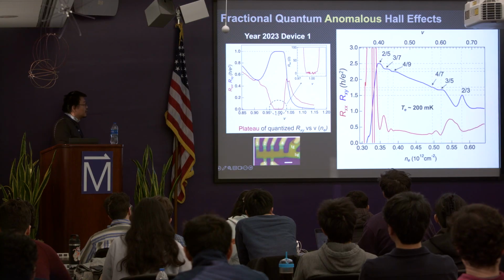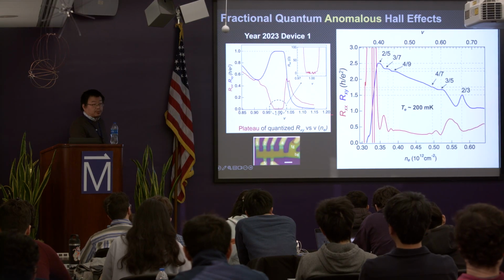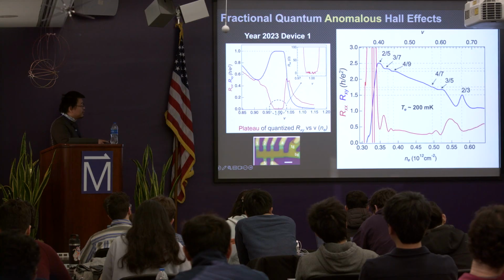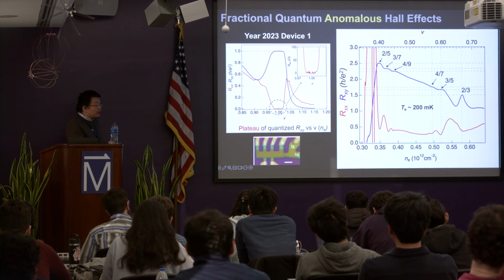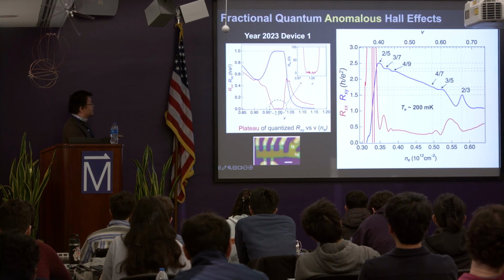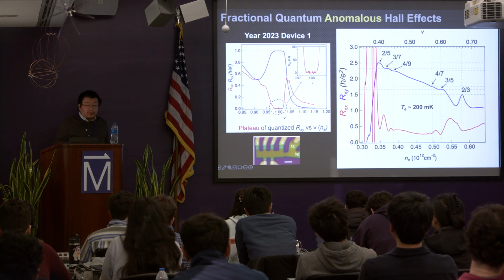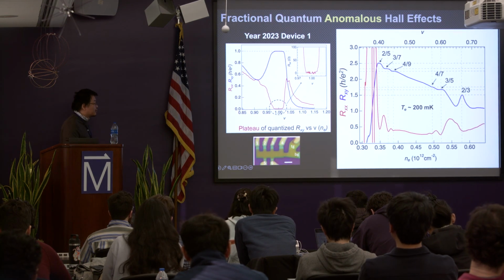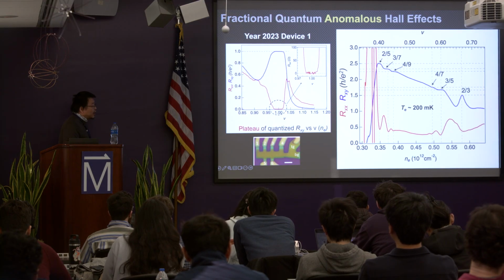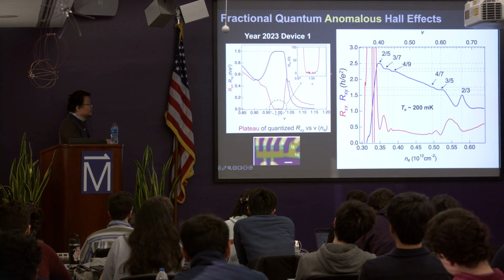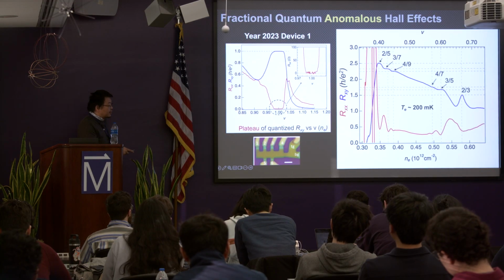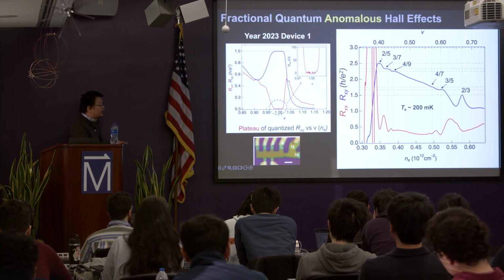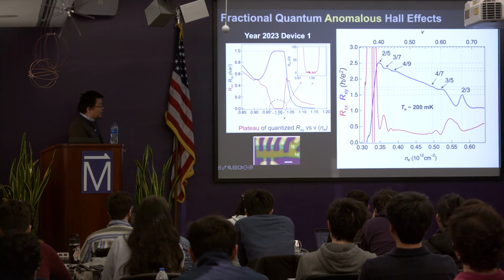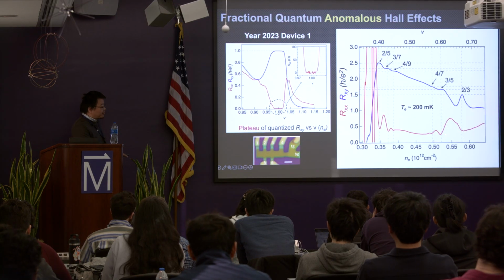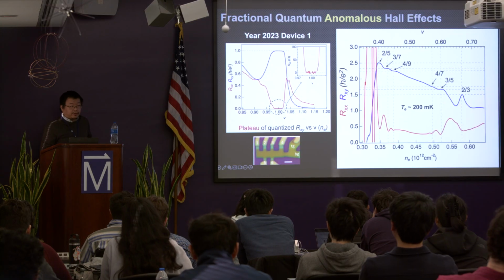If we look more closely by doing line cuts, on the left side is a line cut around filling factor equals 1. You get almost perfectly zero longitudinal resistance, and a very good quantization of h/e². That basically gives you an integer, C equals 1, quantum anomalous Hall state. If you look at the smaller filling factors, you have this multiple staircase structure in the Hall resistance that is aligning with certain fractional filling factors, and it also matches the dips in the longitudinal resistance.